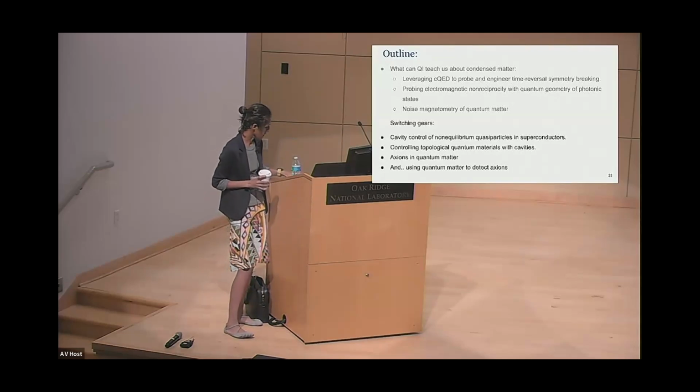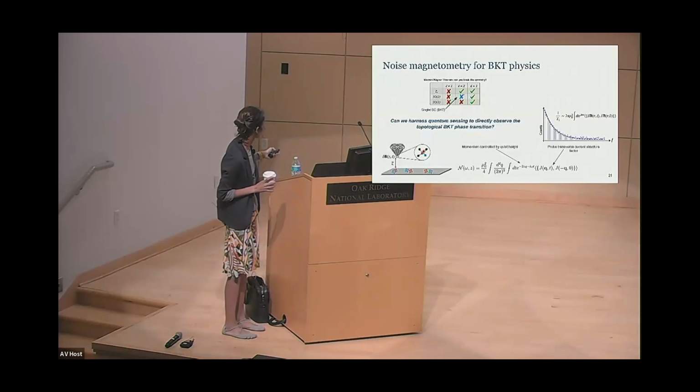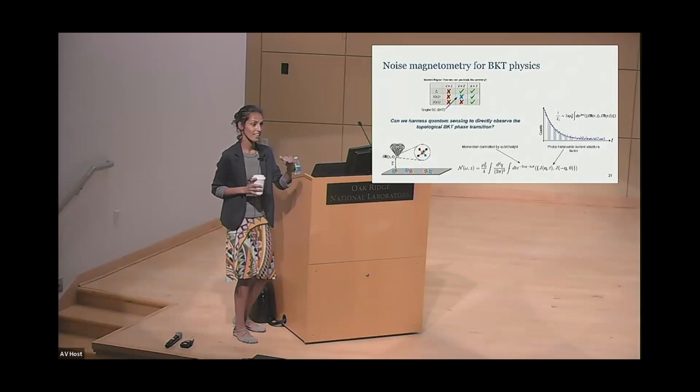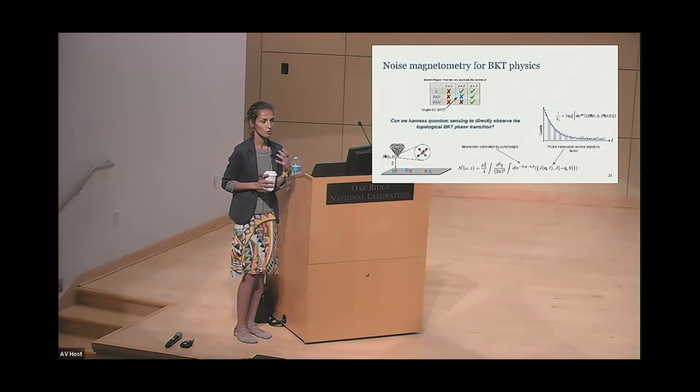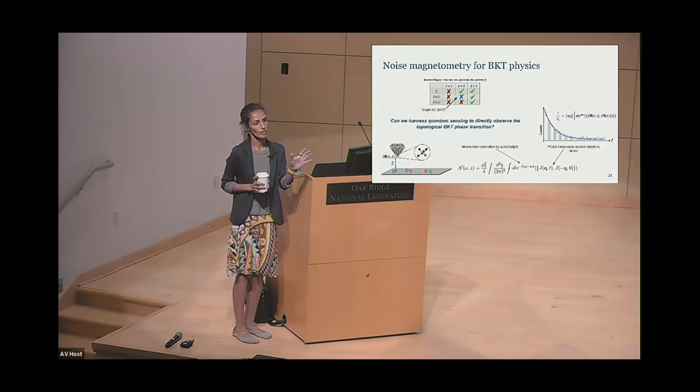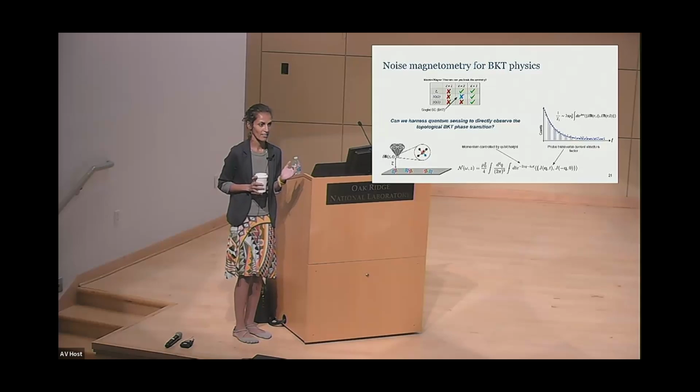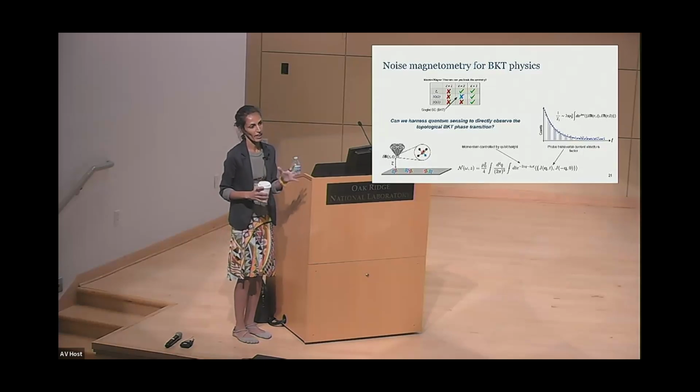Yeah, so, one of the ones that comes up a lot, right? So if you have, this is a view of what this measurement looks like, right? But typically what would happen is that, of course, this could couple to what you're actually interested in. It would also couple to some other crud that's sitting on the surface. Like I said, we're very sensitive to how far it is from the surface. And lots of things get on surfaces, right? Like water gets on surfaces. It sticks there. It messes with that signature. So we have to be very careful that the noise that we are attributing to our transition is actually our transition, not some other thing that's happening. And so you could think about a temperature sweep. That should help, because not everything has a temperature signature, right? You could think about just being able to map that parameter space so that you know exactly what that transition is doing relative to all the other things. Yeah.